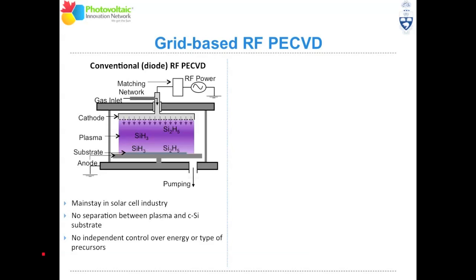So the conventional way to deposit hydrogenated amorphous silicon is with a diode RF PECVD process. And it's a diode process because there's two electrodes. There's an RF powered cathode and a grounded anode. And typically your crystalline silicon wafer will lie on that grounded anode. And there's a plasma formed between the cathode and the anode, and your crystalline silicon wafer is exposed directly to this plasma. There's very little control over the energy or type of precursors that are involved in film growth using this conventional process. And also your substrate is exposed directly to the plasma.